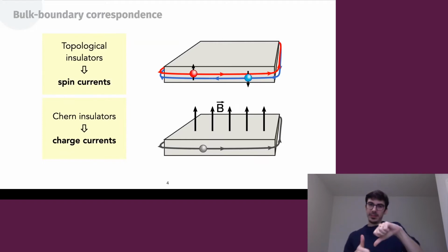So electrons of opposite spin travel in opposite directions, and they are robust. That means they're forced to be there by the underlying topology, and there is some protection to scattering. But the family of topological electronic materials is much, much wider than topological insulators.